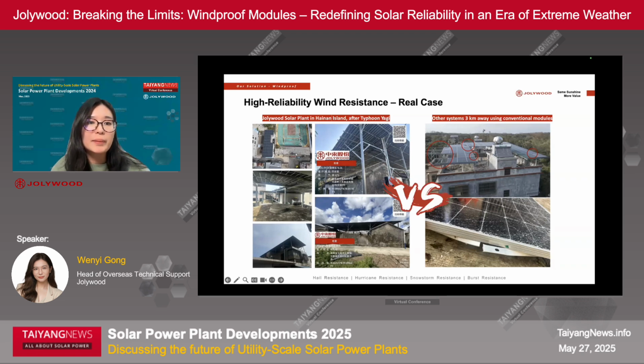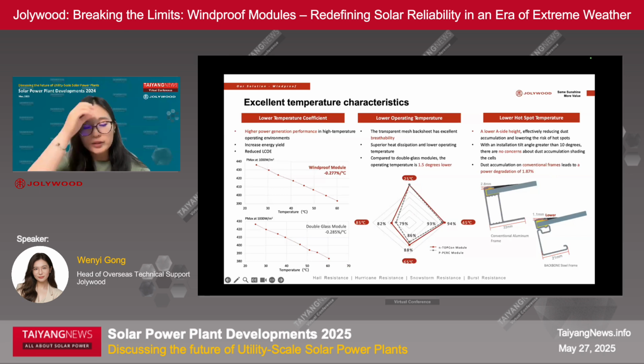So except for the good reliability, it also has excellent temperature characteristics. It has a lower temperature coefficient compared to the double glass due to the thermal dispersion ability of the backsheet, and the operating temperature of the module is also lower. We performed one year of on-site testing comparing different modules in the system, and we monitored the backside temperature for the whole year. We've seen that on average the windproof module has a 1.5 degree lower operating temperature than the dual glass one. And also, due to the lower A side, it helps to eliminate the shading issue by dust at the edge, so it can help to improve the hotspot issue at the edge.